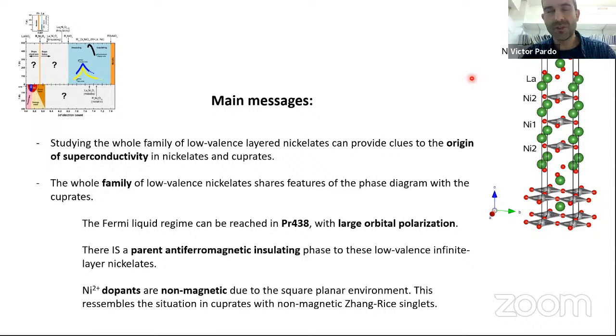To bring those oxygen p bands closer to the Fermi level, you need to dope it. When you dope neodymium nickel O2, you move those bands closer to the Fermi level. But going to the monolayer, you don't do that. You just get rid of the d_z² band, basically.